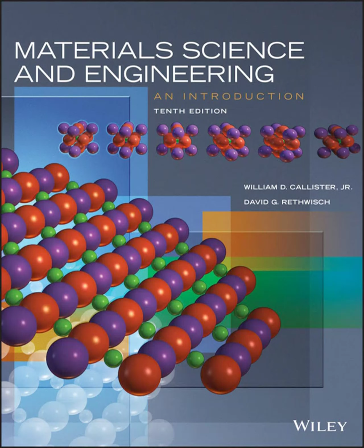So, to quickly recap for everyone listening, we saw that metals typically corrode via electrochemical processes involving oxidation and reduction, and the rates are governed by factors like polarization. We explored the fascinating phenomenon of passivity, where some active metals can form thin, protective oxide films, giving them excellent corrosion resistance. We learned that corrosion isn't monolithic. It manifests in many distinct forms: uniform, galvanic, crevice, pitting, intergranular, selective leaching, erosion corrosion, and stress corrosion cracking, each with unique characteristics and prevention strategies. And we touched on hydrogen embrittlement as a related failure mode.